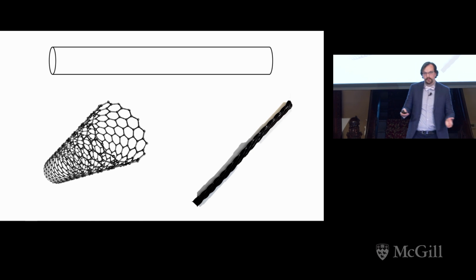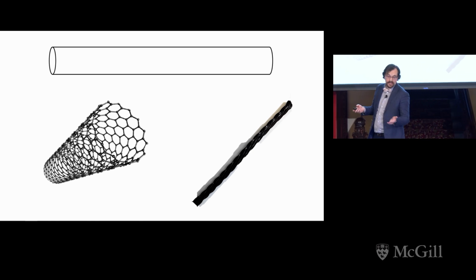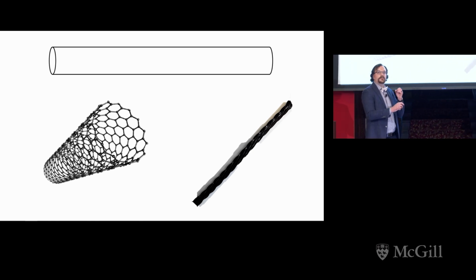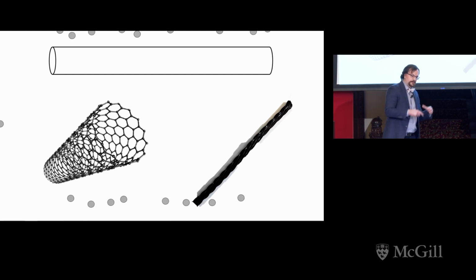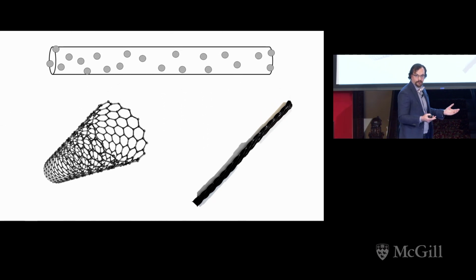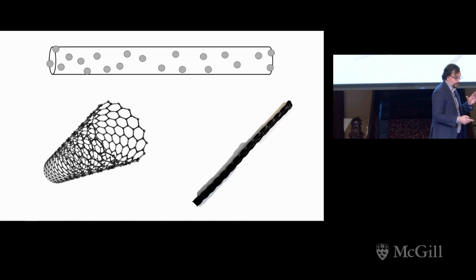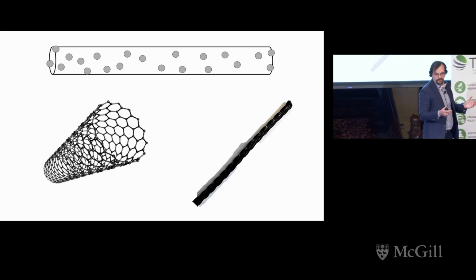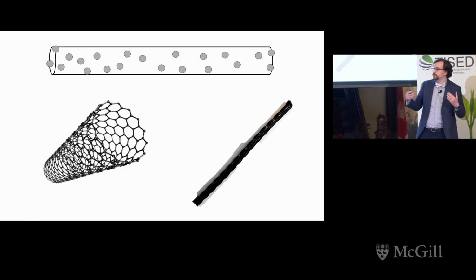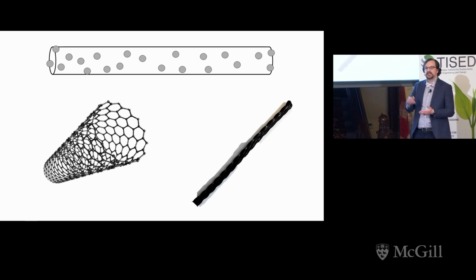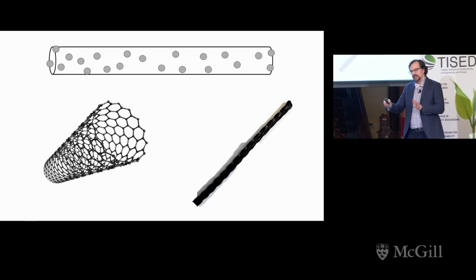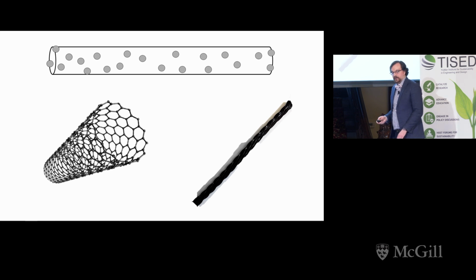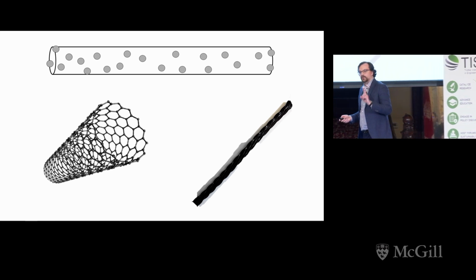Now, why would you use this carbon nanotube? Well, they have great surface area, and this tubular structure helps form small nanoparticles, which we like. Also, the great part is the literature shows that carbon nanotubes themselves can actually assist the catalyst with electron transfer, increasing conversion. However, for our catalyst, nickel, there's one slight problem.